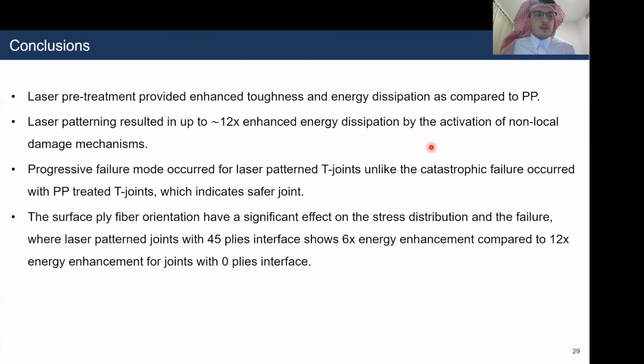So in conclusion, the laser pretreatment technique provided enhanced toughness and energy dissipation as compared to PP. The laser patterning resulted in up to 12 times enhanced energy dissipation through the activation of non-local damage mechanisms such as adhesive ligaments and substrate failure. Progressive failure was recorded for laser patterned T-joints. However, catastrophic failure occurred with PP treated T-joints, and this indicates that a safer joint can be produced using the laser patterning pretreatment.